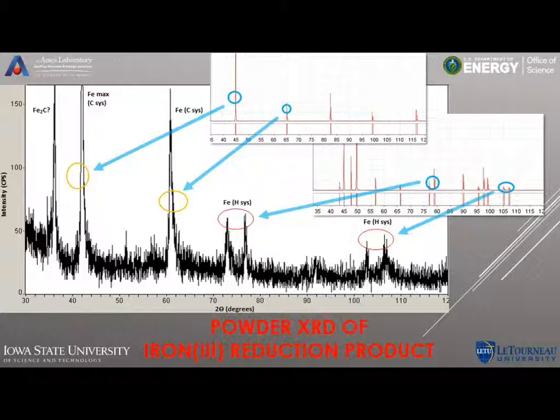Basically, XRD works by taking an X-ray beam and directing it on a sample, and the X-rays interact with the atoms in that material, and they are deflected in a specific pattern, which indicates the crystal structure that the material has. And that crystal structure can be matched up to specific metals and their phases. And so in this case, I had to grind the material into a powder, and it was very difficult with this harder metal to do that. And so the readout just wasn't as good. But it does still look like I was matching the peaks to pure metal peaks, as you can see, just in two different phases there.